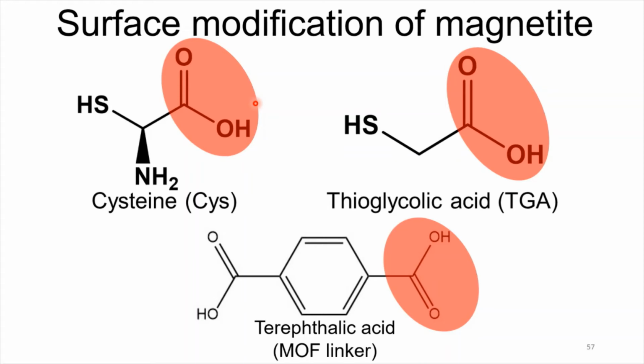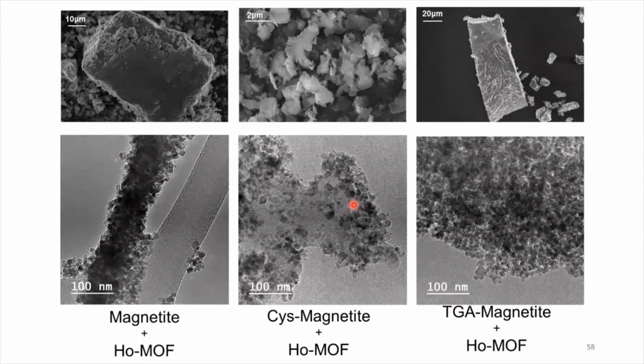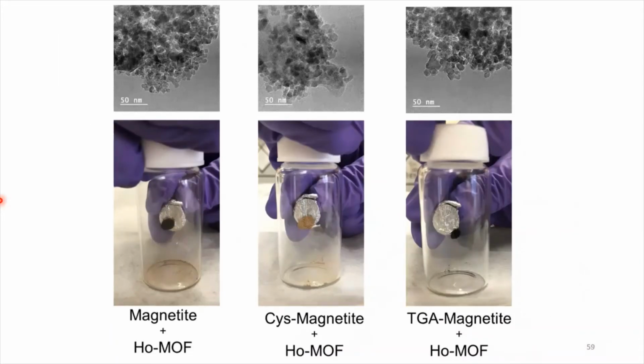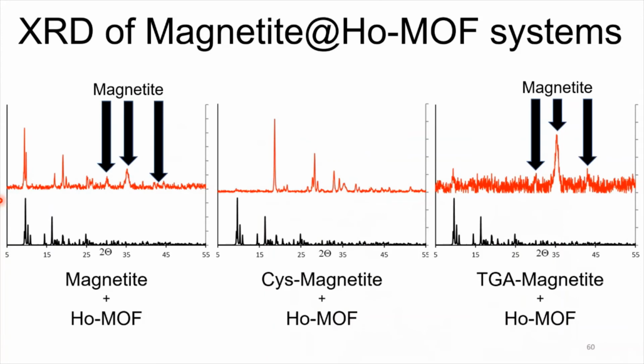And some quick results that we got before: these are SEM and TEM pictures of pure magnetite with the MOF around it, cysteine magnetite with the MOF around it, and the TGA magnetite with the MOF around it. As you can see, the best result by far is the TGA. Even though we still see big crystals, it seems that they are composed of little particles, the same with the magnetite. All three of these are actually magnetic, which is very promising. This is exactly what we wanted. And through XRD, we can confirm both the presence of magnetite and the presence of the MOF.